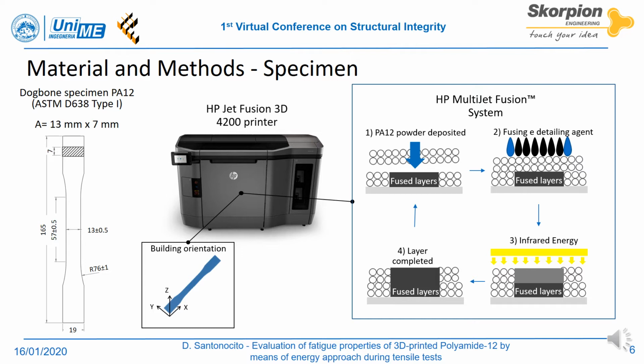A source of infrared energy, usually planar lamps, pass over the surface of the bed, allowing the powder fusion. The process continues layer by layer up to the completion of the component. The specimens were printed adopting the fast printing profile, which ensures a rapid printing process, but with lower mechanical properties compared to the mechanical profile.